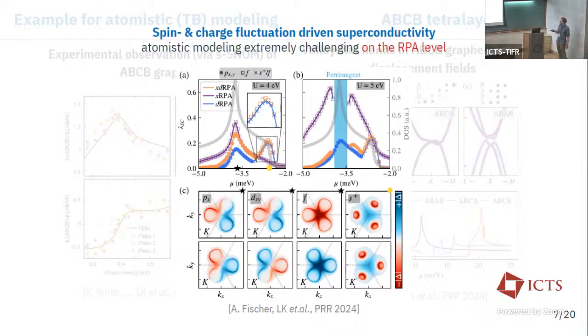Now, on a side note, we found that local interactions strongly drive F-wave superconductivity in this material, which is a gap that looks like this here around the 2 valleys, whereas long-range Coulomb interactions drive P and D-wave superconductivity, which are almost degenerate. And the reason for that is that long-range interactions in momentum space work within a single Fermi pocket in a single valley, and therefore you need a sign change in the single valley, whereas with the local interactions, you can have the sign change in between valleys.